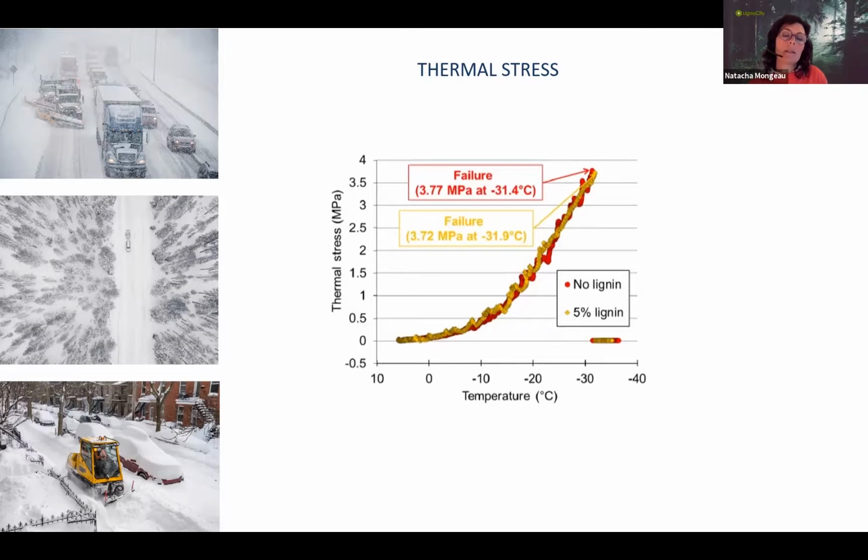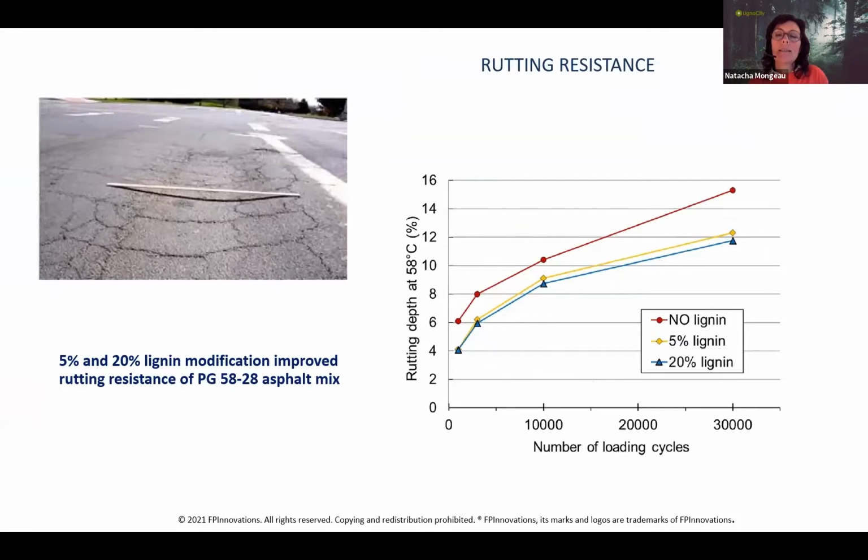This chart illustrates the rut depths of the PG 58-28 asphalt versus the same mixture with 5% and with 20% lignin substitution. As is apparent, the lignin substantially improved rutting resistance of the mix for all numbers of loading cycles. This really highlights how the modification of asphalt mixtures with lignin improves the performance of the asphalt as compared to